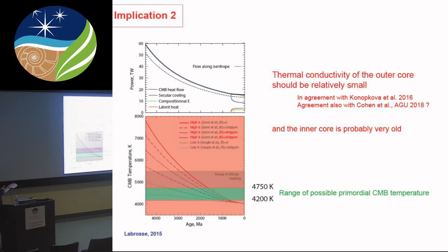This is completely out of range. This means that the core is going to melt everything on its path, because you have too much heat. You go out, you're above the liquidus, you're above the melting curve of bridgmanite. So you're going to melt everything, and the flux is going out. You can't keep a core at that given temperature for 1 billion years. It's totally impossible. So you have to start there, and you have to go to that point now where we are.